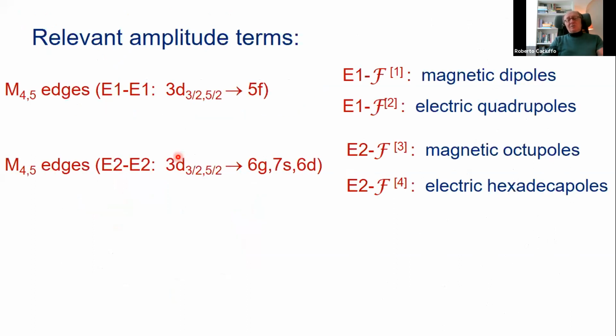The relevant amplitudes, the important edges are again M4 and M5, because the transition is to an empty 5f state. At these edges, the dipole-dipole terms of the transition have essentially three terms: a trivial one, which is probing the charge, one which is probing magnetic dipoles, and another which is probing electric quadrupole. At the quadrupole edge, instead,